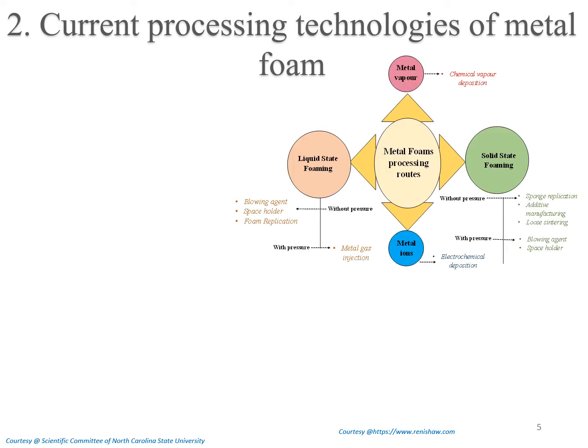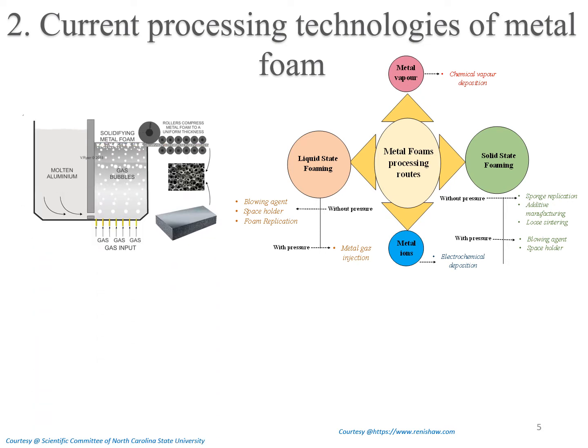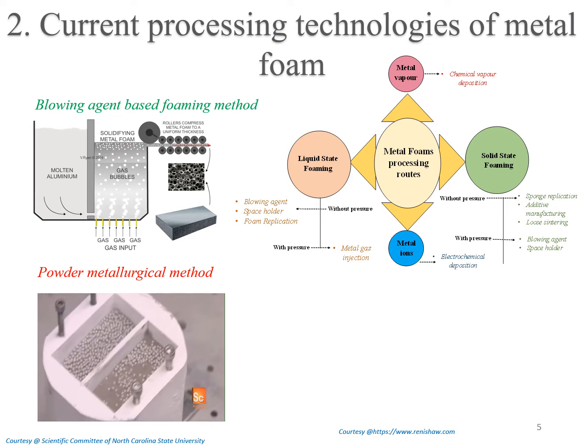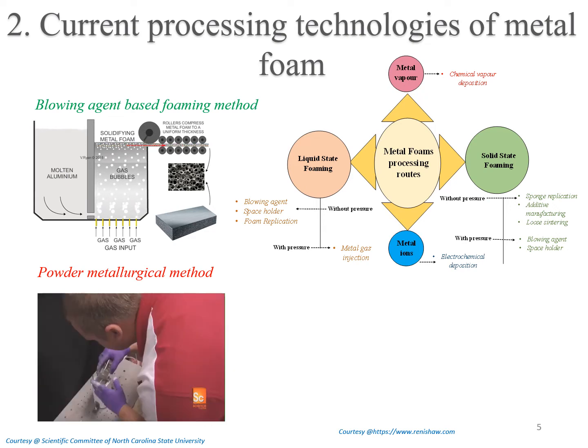With growing popularity of metal foam, various methods for making these materials are available, as shown in the figure. Some techniques start from specially prepared molten metals with adjusted viscosities. Such metals can be foamed by injecting gases or by adding gas-releasing blowing agents that decompose in-situ, causing the formation of bubbles. A further class of techniques, also called the powder metallurgical method, begins with a solid precursor containing a blowing agent, prepared by mixing metal powders with a blowing agent and compacting the mix.